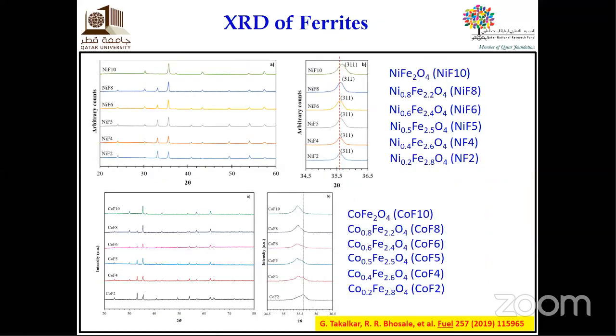The first one is the XRD of ferrites. Now you can see two sets here. One is the nickel ferrite set and the other one is the cobalt ferrite set. You can see, for example, in nickel ferrite, we have nickel 0.2, 0.4, 0.5, 0.6, 0.8. So we actually played with the chemistry. We put 20% nickel in the iron oxide, then 40% nickel, 50% nickel, 60% nickel. So what we're doing here, we are actually replacing the iron part, which is less reducible, or you can say less active, with the nickel part, which is more active. So we synthesized six nickel ferrites, different morphologies and different crystal structures. And similarly, we have the cobalt ferrite. So the XRD tells us that yes, whatever we have planned, we have synthesized successfully.